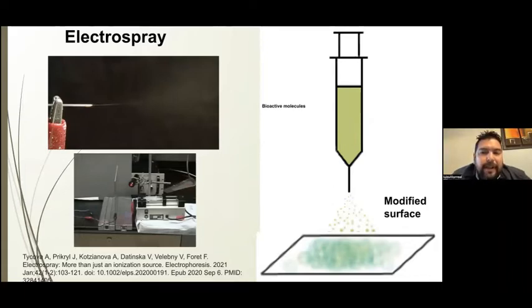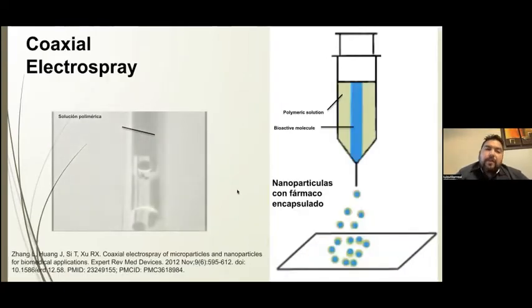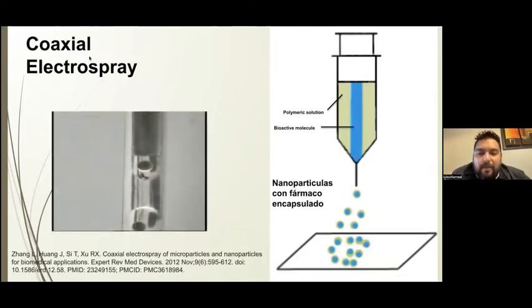If you want to create fibers, you use high viscosity solutions, and if you want to have particles, you prepare with lower concentrations of the polymers. And also, finally, you can have a coaxial electrospray where you can create nanoparticles, but with a core-shell morphology.